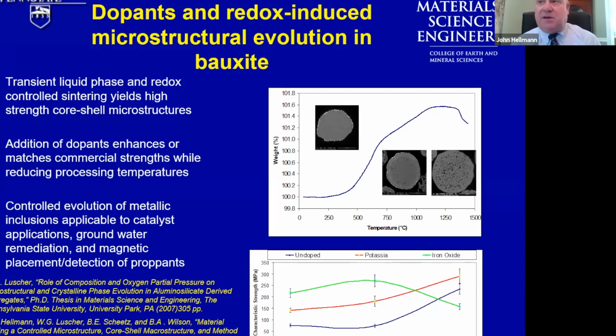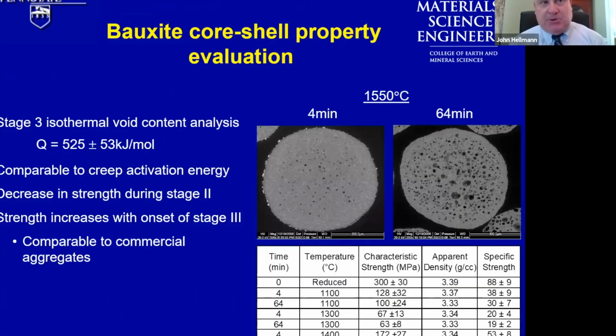So we dug further into the literature going back to the 50s from the refractories industry, in understanding the interactions between fire clay refractories and bauxite-based refractories with molten iron, steel, and slags. And what we found is that the occurrence of these metallic iron decorations on the surfaces of our particles was entirely expected if we understood more about the oxygen partial pressures through the course of the processing cycle in which these proppants were manufactured. And so we thought this would be an opportunity.